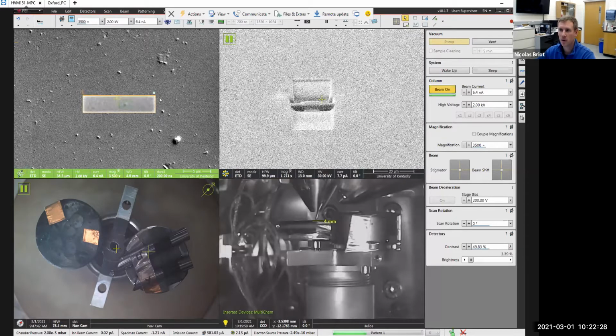So again, the whole goal of doing the cross-section this way is that this surface of the material has not experienced any physical damage. It wasn't polished or cut or anything. It's just the original surface. I deposited some gold palladium on it, so we should be able to see that as well in the cross-section. That's just to help with conduction. But what's below should be the original glass rod surface. So we're trying to get rid of that question mark in the equation: how much did we damage with the polishing and grinding? We could still see potassium for a few microns, so we didn't get rid of all of it, but maybe we did get rid of some of it.